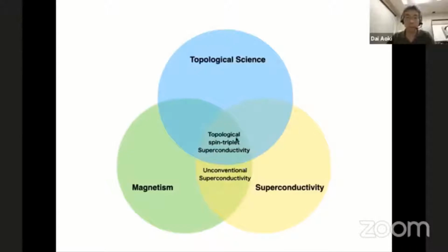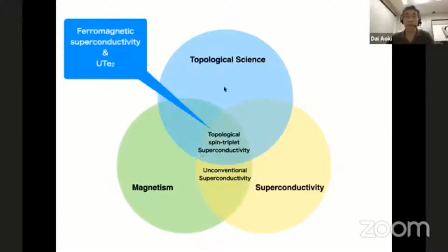Here, topological spin-triplet superconductivity is located, and ferromagnetic superconductivity is spin-triplet superconductivity, and also uranium ditelluride is a strong candidate for a spin-triplet superconductor. So it's located here. The uranium compound is really a good playground to study topological superconductivity, and to study this region, uranium compounds are a good target material.